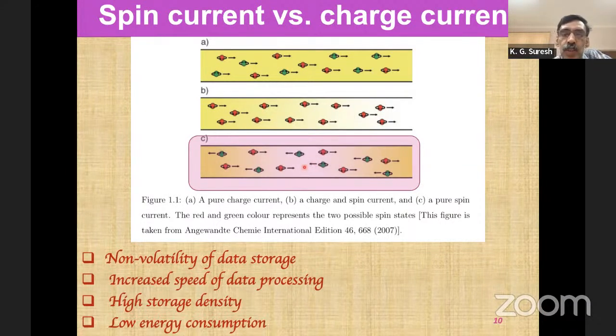Whereas with this kind of situation, one can mimic a case where one type of spin moves in one direction and the other type of spin moves in the opposite direction. How to get it? Suppose you have a very strong spin momentum coupling, then this is guaranteed, because spin and the direction of motion are coupled, and you are guaranteed to have this kind of thing. There will be no net charge effect, there is no scattering of these forward moving electrons to the backward side, and therefore you will have almost resistance-less transfer of spin from one to the other, and that results in what is known as a spin current. So this is a pure spin current, whereas this is not. Even this is a charge current, not a pure spin current. This is the only thing which is a pure spin current.